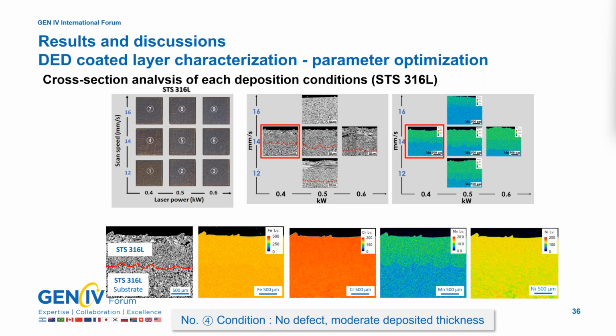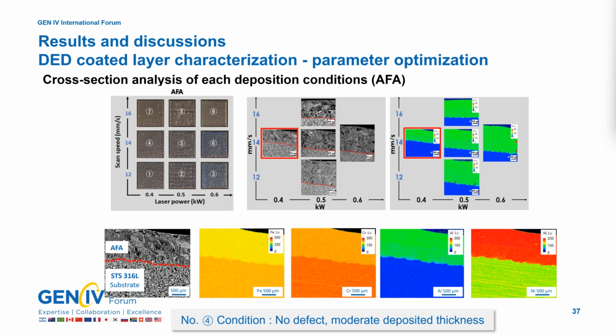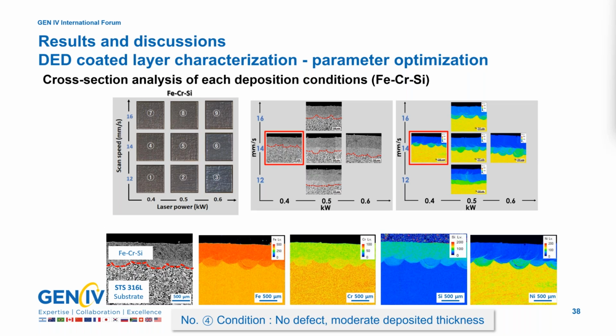To select the optimal parameters, the cross-section of the surface-coated layer was observed. Similar to the single-line analysis, considering the dilution and layer thickness, condition 4 was determined to be the most suitable. For the AFA coated layer and iron chrome silicon coated layer, the optimal parameter was determined to be the same. Also, the EPMA mapping results were similar to those of the single line analysis.